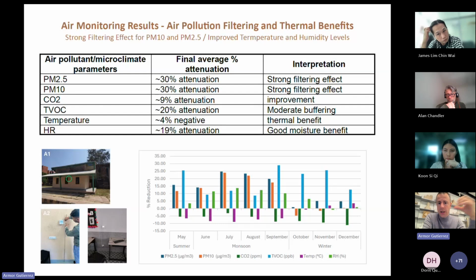So it has very good moisture buffer value, which means that it's able to absorb humidity and then release that humidity back either outside or back into the room when the humidity level changes. And that effect might be getting some of that compound, which is generated externally, entering the building and then being trapped by the blocks. Likewise, there is a very good attenuation of TVOC compounds and a very good reduction in humidity levels, which was something that we were expecting.